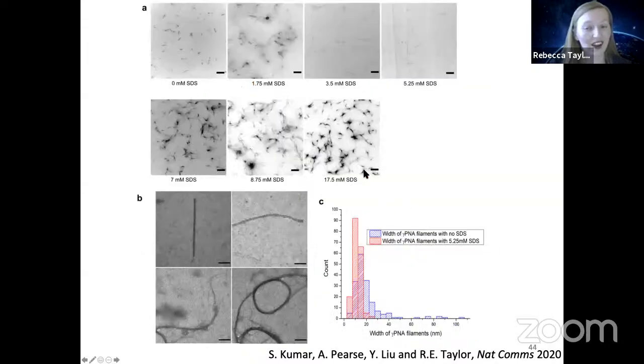And then because it's not just like DNA, we showed that we can learn some lessons from proteins. So if we introduce a surfactant, SDS, we could show that we could actually break up these filaments. And you can see we've got thick clusters, and then it gets thinner and thinner, and this is much more, it's not quite monodisperse, but it's a much tighter distribution of diameters. And so we can see in this histogram below that we can break them up and actually see individual filaments and then probably 2 filaments or 3 filaments stuck together.